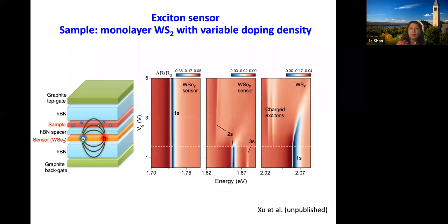So here is a tester system. We have a monolayer of WS2 as a material where we can change the doping, and then we look at the response of the sensor to get an idea. So let's look at the right panel first. This is the optical reflection contrast from the monolayer of WS2 directly. And this dashed line is the voltage that you're putting charge in with.